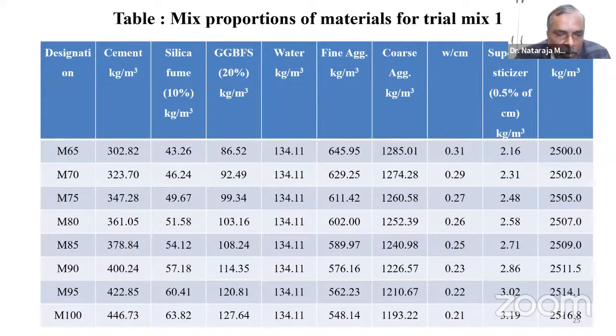As long as you have the standard concrete, yes, the cement content should not be more than 450 kg, minimum being 300 kg. And even with that 300 kg minimum, I'll be using only 100 kg of cement, my dear friends, 200 kg of supplementary materials, but 300 kg of cementitious material.